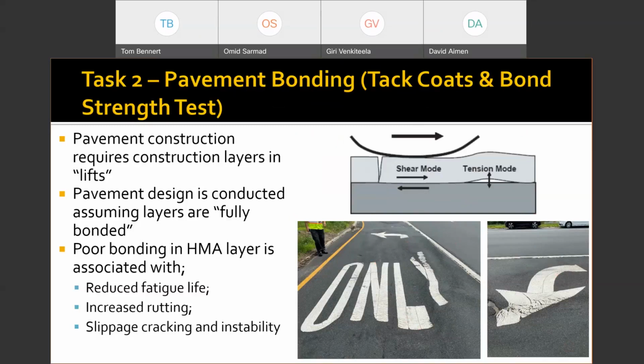Or you can also have a situation, shown in the upper schematic here, a tension mode, where we just don't have any bonding. And what ends up happening is that the entire surface lift has to take up all of the stress. In doing so, you get a significant amount of bending, a significant amount of deflection, and that will cause the material to crack much sooner. So the idea is to make sure that we get bonding of these layers to reduce this slippage, to reduce this potential for premature failure in that surface area.